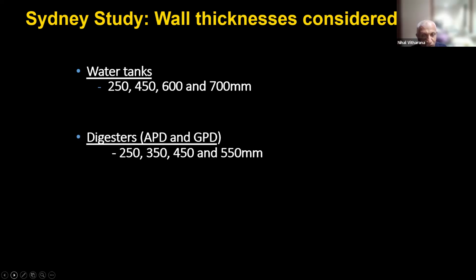They are not exothermic. That means they don't produce heat when the sludge is digesting. But when you look at APD, acid phase, they put raw sewer into them. But when it comes to GPD, the sewer is heated at 36 degrees throughout its decaying process. So we can't just take water tank temperature gradients and put them to a digester. That's the problem. Yeah, next one, please.